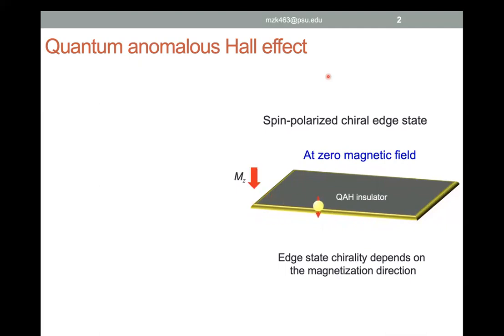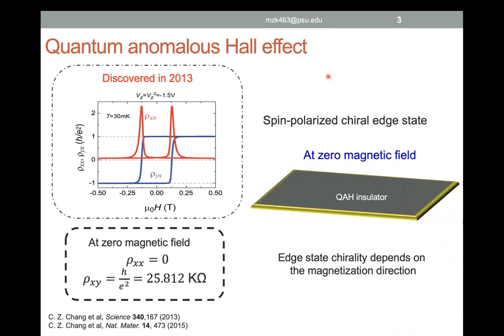The experimental signature for these chiral edge modes is that if you do normal Hall measurements, measuring the longitudinal and Hall resistances, in the Hall resistance you will see a quantized value accompanied by a vanishing longitudinal resistance. This quantized Hall resistance changes sign when the magnetization is reversed. This was observed experimentally by Cui-Zu Chang and colleagues in 2013.